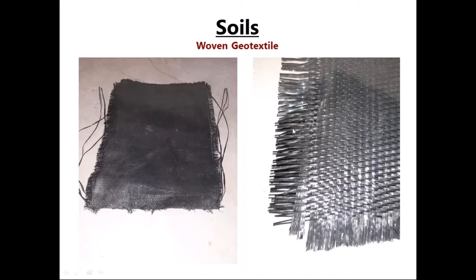So this type is a woven polypropylene. So you can see the individual polypropylene strands that are weaved together. And these are very strong. Geotextiles are typically used for stabilization below roadways, below slabs. So they provide good stability. The one problem, some of them do not allow water to pass through them very easily, so they can collect water on top of them. But they're typically used for stabilization over softer subgrade soils.